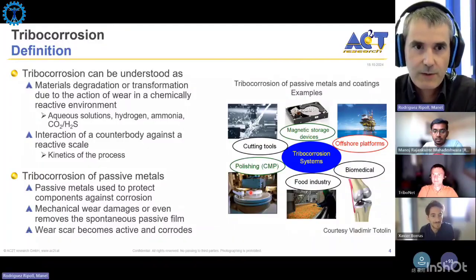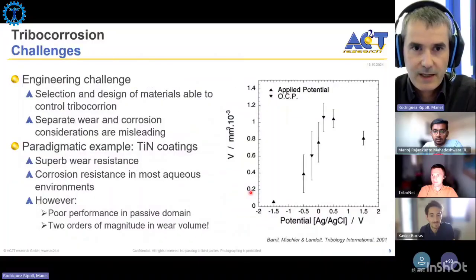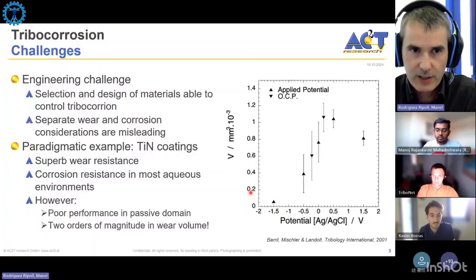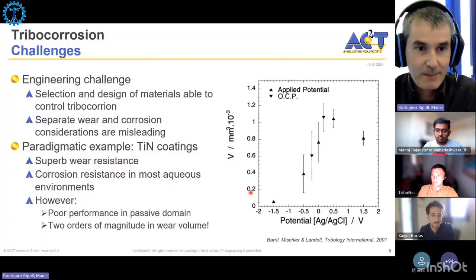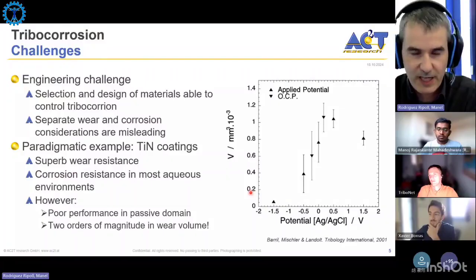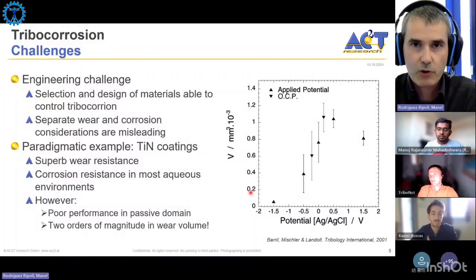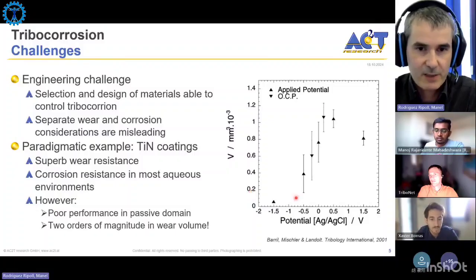And the main challenge when we talk about tribocorrosion is that to select materials that are able to control tribocorrosion, to be tribocorrosion resistant, we cannot rely on separate corrosion and wear evaluations. So if we take a material that is corrosion resistant and we take a material that is wear resistant, we cannot automatically assume that this material will be resistant against tribocorrosion. And one paradigmatic example is titanium nitride coatings. This is a coating that has excellent wear resistance, is used in many cutting tool applications. It also has very good corrosion resistance in most aqueous environments, but is a material that is very prone to tribocorrosion.